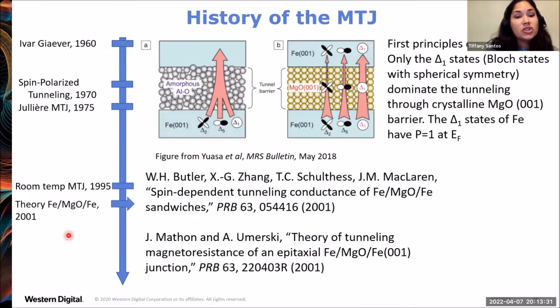Okay. So in 2001, there was a first principles calculation saying that if you use magnesium oxide tunnel barriers with iron electrodes, the top and bottom here, and you have this specific crystallographic orientation for your barrier and electrodes, then you'll get a special situation where you have fully spin polarized electrons in the iron tunneling across the barrier, and in the MgO, they will give a lower barrier height, making it easier to tunnel for these fully spin polarized electrons. So this particular material set can give you a TMR of over 1,000%.